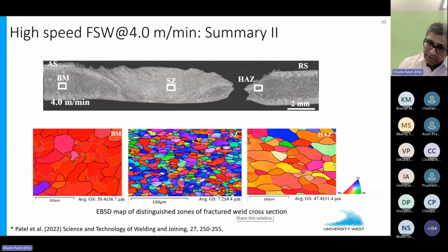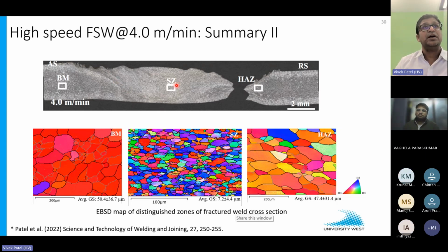Then we also tried to understand whether high speed welds are the same as conventional welding speeds of friction stir welding, up to 1 meter per minute or 2 meters per minute. We looked at the microstructure through SEM, and we found that the stir zone, due to severe plastic deformation, because the parameters we used were so aggressive, more than 3000 rpm and around 8 kilonewton downward force, created a lot of plastic strain in the weld nugget, and that allowed grain size reduction down to 7 microns from 50 microns in the parent material.